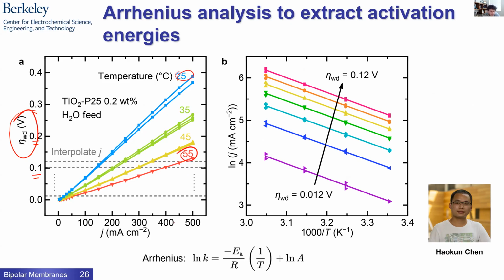Okay. Now we can interpolate at a constant driving force. So one of the things about electrochemistry that's a little different than most thermocatalysis reactions is we control the delta G of the reaction. That's what we're controlling here by turning up that voltage. We're changing the delta G of reaction. We're changing the driving force, and we're looking at how the rate depends on driving force. That's what one of these curves is.